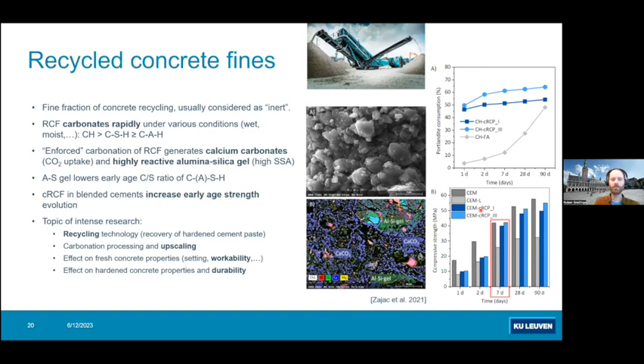However, there's still quite a lot of research to be done to optimize this. First of all, the recycling technology, trying to recover as much of the hardened cement paste from the fines, so to separate it from the sand, basically, is really needed. The more sand you have, the more filler, the more abrasion on any milling installation, and so on. So getting rid of the sand is very important.